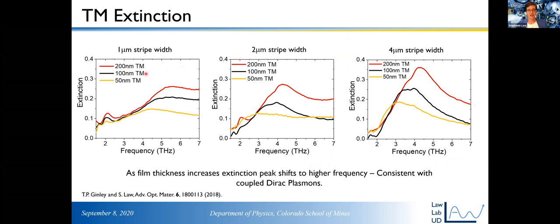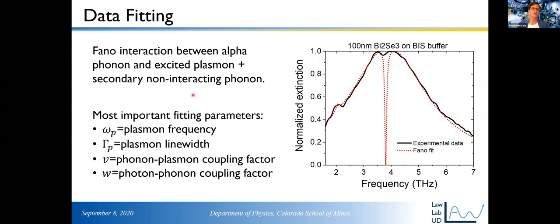So as I said, we're gonna make 3 different film thicknesses, 50, 100, 200 nanometers, and then 3 different stripe widths. We're gonna measure the extinction for all of them. And what you see is you can see this peak is shifting. The plasmon peak is shifting pretty much like we expect as we change the stripe width and as we change the film thickness. But this is consistent with coupled Dirac plasmons, but we really need to actually extract the peak position, right? You can't just look at this and say, ah, yes, we excited what we wanted to see. So we do some modeling.